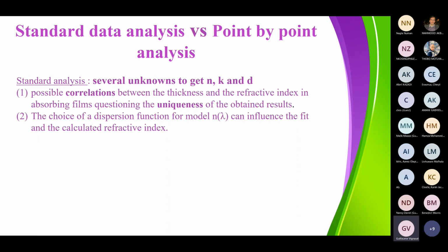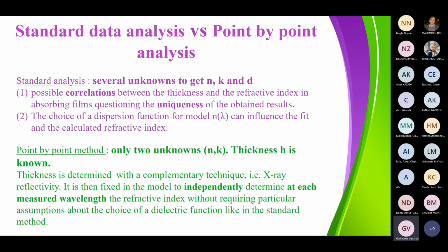In fact, the problem with this standard data analysis is that, particularly for the VO2, you can have a correlation between the thickness and the refractive index, because the film is absorbing, questioning the uniqueness of the obtained result. And secondly, the choice of a dispersion law to model n(λ) can influence the fit and also the calculated refractive index. Then we have tried a new method called the point-by-point method, where we have only two unknowns, n and k, the real part and the imaginary part of the refractive index, and the thickness is known. The thickness is known because we measure X-ray reflectivity on the samples, and we extract the thickness from this technique.